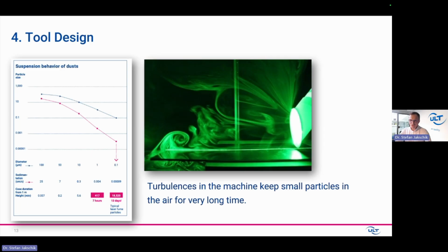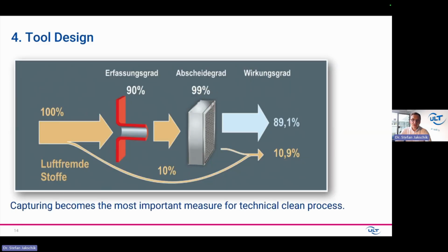We made a visualization of this process, shown on the right side in green, where we put a certain light on the air and a lot of particles in order to see how the particles are captured. But for the machine designers here in the round, I want to talk about two or three very important topics to be taken into account. The one is you have to make sure that you capture really everything or nearly everything. So in this picture, if you have 100% of the particles and you just capture 90%, you still have more than 10% of particles in the air which could degrade the battery in future operation.